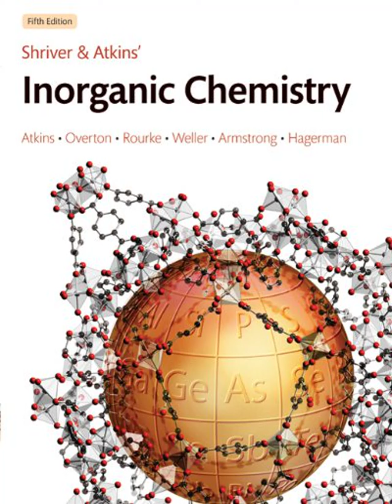The small size and relatively higher electronegativity of lithium compared to the others leads to significantly more covalent character in the Li-C bond. They also have fascinating structures. They don't usually exist as simple monomers but form aggregates, clusters like tetramers, (LiR)4, or hexamers, (LiR)6, held together by electron-deficient multicenter bonds. The exact structure often depends on the R group and the solvent.